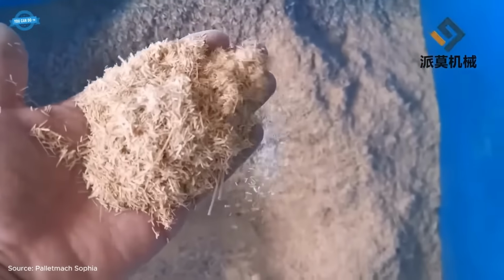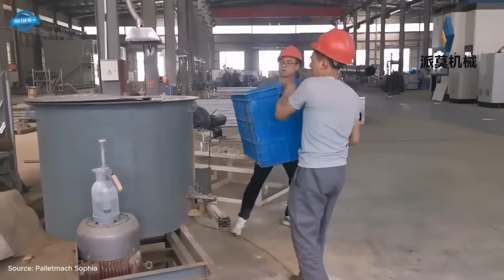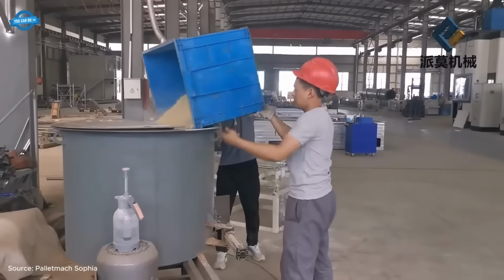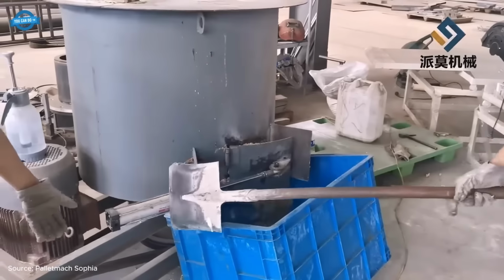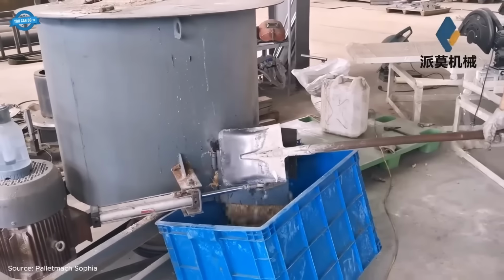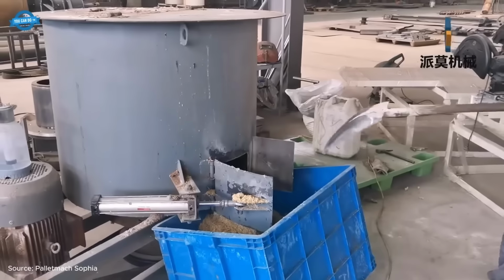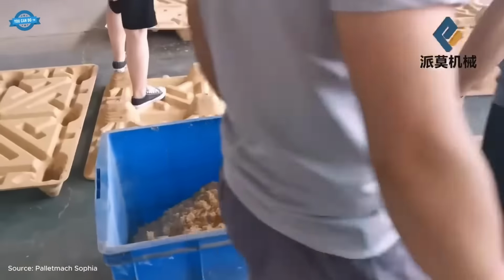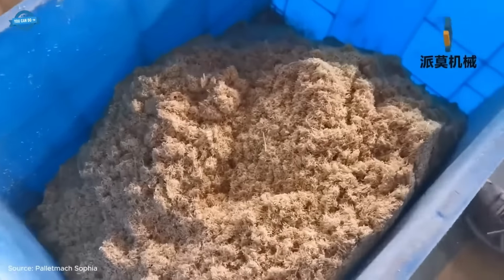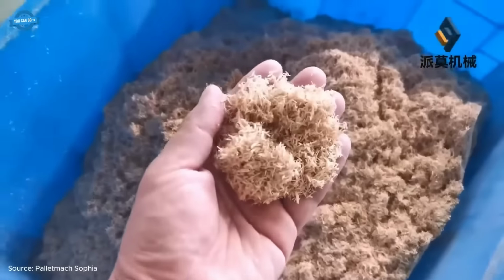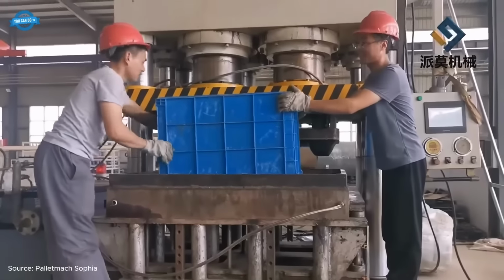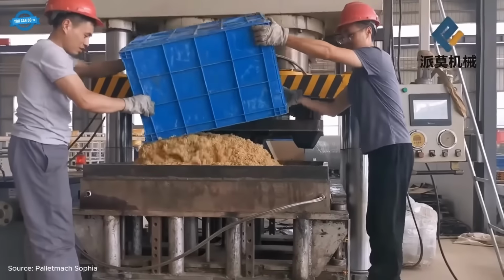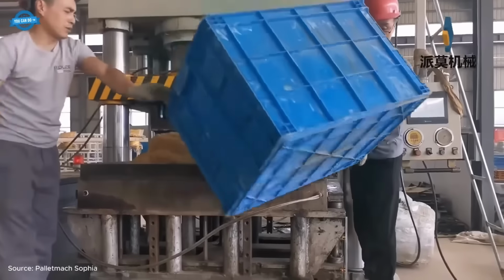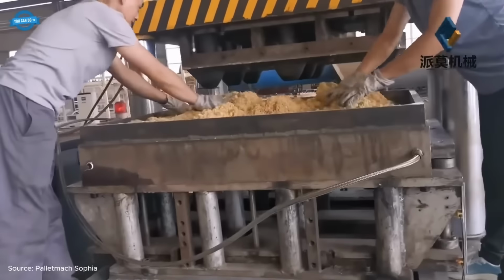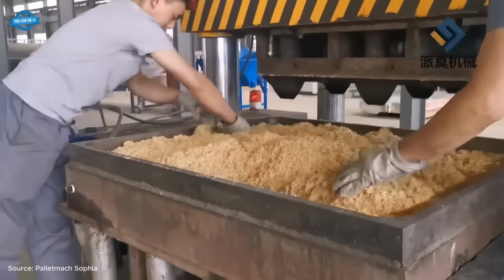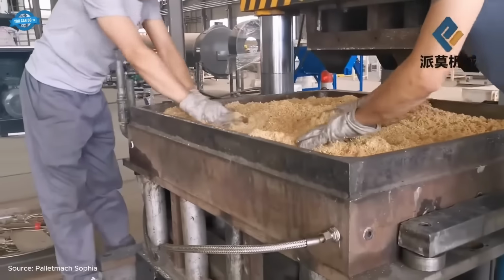This bamboo pallet test explores the reuse of bamboo waste to create a durable, high-performance logistics solution. Processed bamboo residues are engineered into composite panels, forming a pallet with a smooth, uniform surface and consistent structural strength. Load testing confirms good compression resistance and dimensional stability, making the pallet suitable for handling, stacking, and transport.